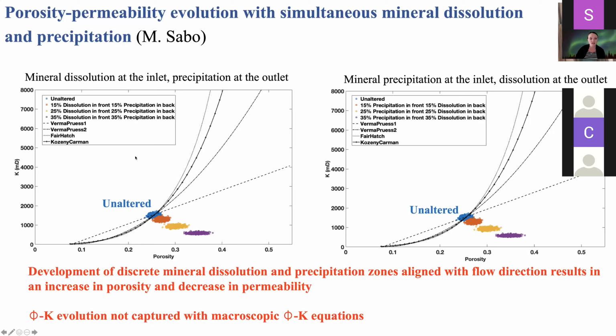And what we find is that this results in an increase in porosity, but a decrease in permeability. So basically, even though you're going through a dissolution zone that would increase those, you are constricted by flowing through the precipitation zone that has decreased the pore throat sizes. Again, we have these macroscopic porosity permeability relationships shown as the black lines, and you'll notice we're not able to capture this at all with these relationships.